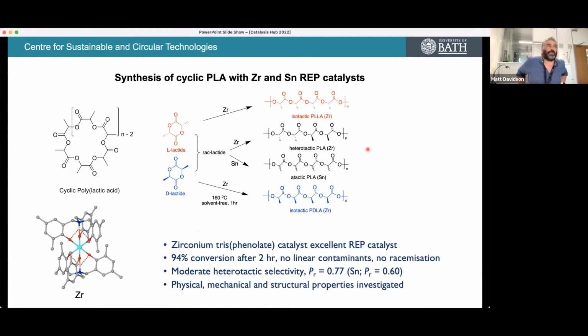So we were encouraged to look at these zirconium catalysts for ring expansion polymerization of lactide. And again, I won't go through too many synthetic details here, but similar to the tin examples published by Kricheldorf, we utilize similar conditions: 160 degrees, typically solvent-free, 1 or 2 hours reaction time. So reasonably reactive systems. With this zirconium trisphenolate catalyst, we can take L-lactide or D-lactide or the racemic mixture of the two. We can make isotactic rings, we can make heterotactic rings, because remember, the zirconium catalyst is heterotactic. If we use the tin version, we get an atactic polymer microstructure. And if we take the D-lactide, we get isotactic PDLA.